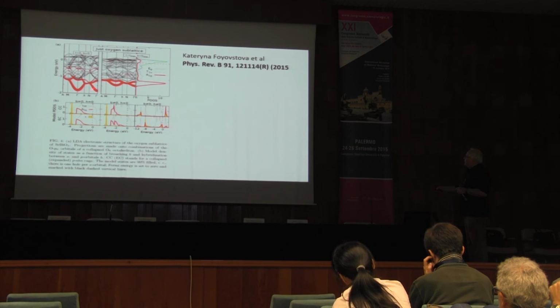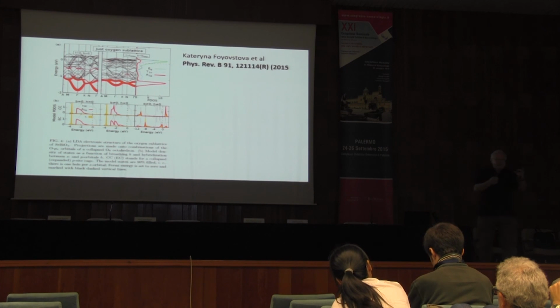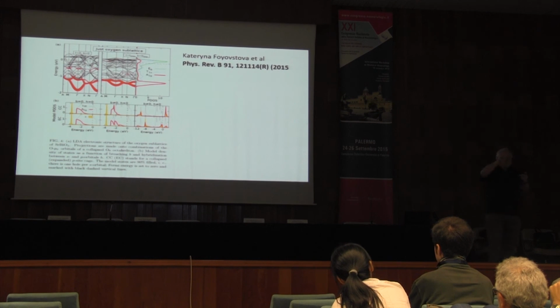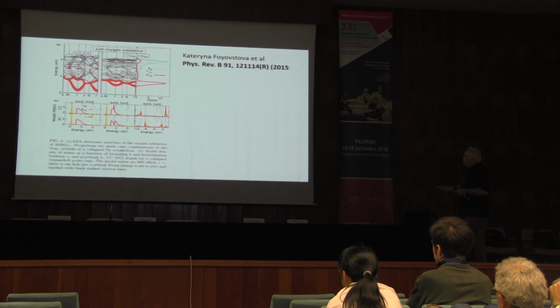Right, that's what I said before. Now you put in the disproportionation, the shorter and longer bond lengths, and you put in the tilting of the octahedra, and suddenly you get something rather narrow over here.